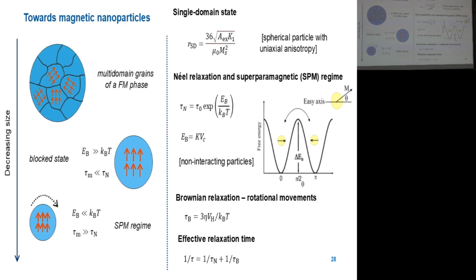So at a temperature high enough, or for particles small enough, we are entering the superparamagnetic regime. I wouldn't say that there are superparamagnetic particles. There are no superparamagnetic particles. There are ferro- or ferrimagnetic, magnetically ordered particles that can be either in the blocked state or in the superparamagnetic state or regimes. But this description is of course dependent on the time scale of your view.